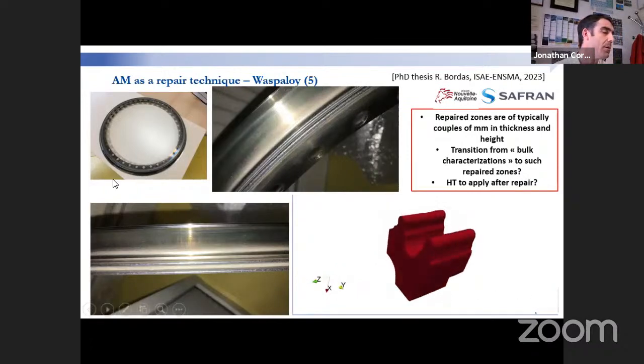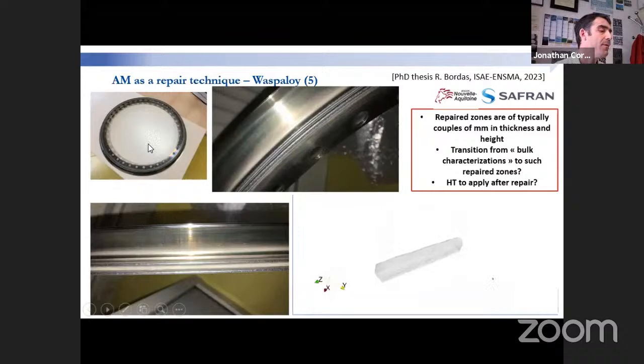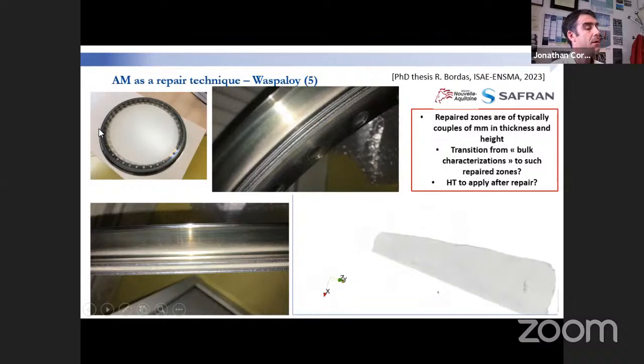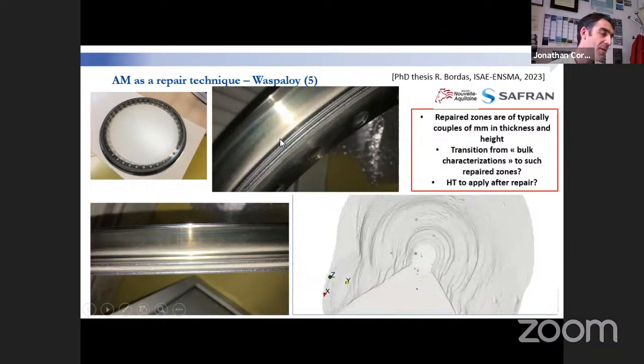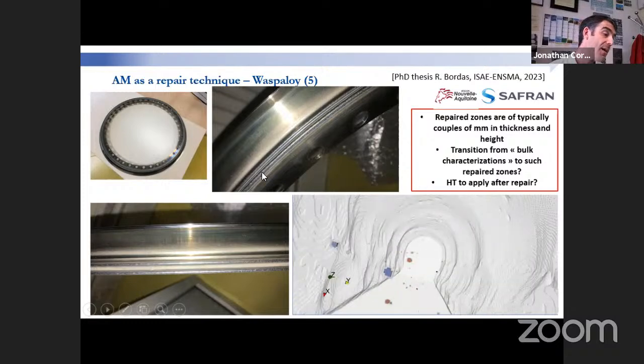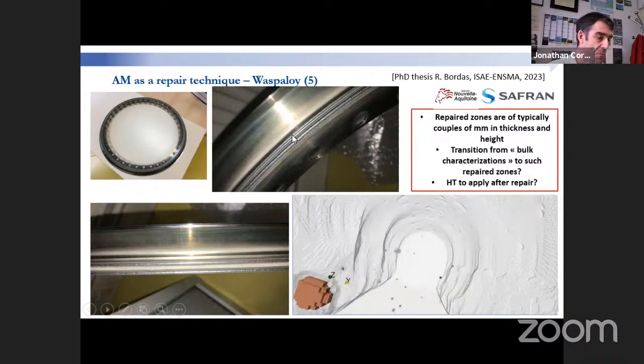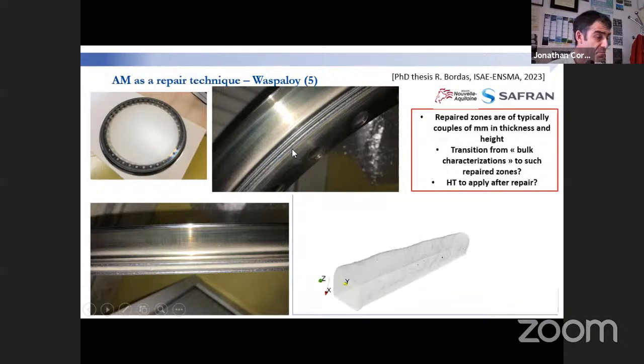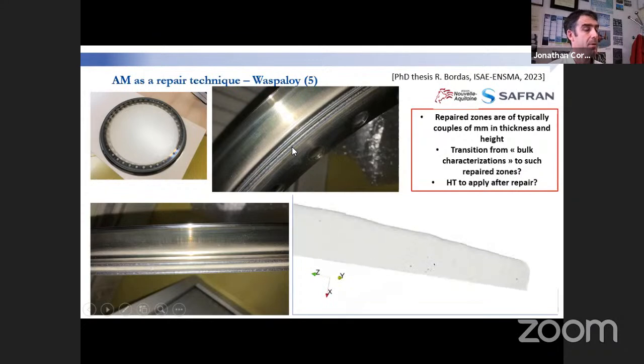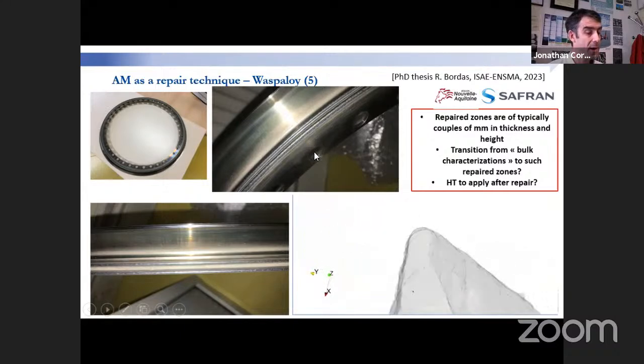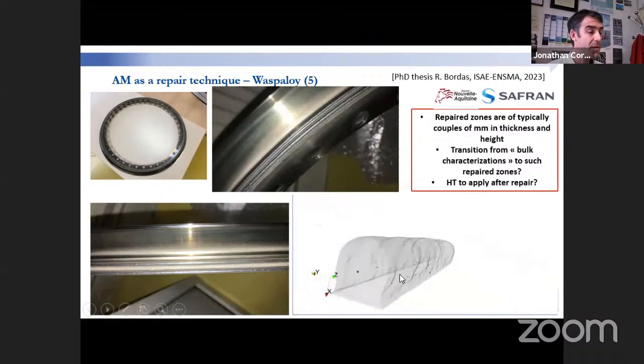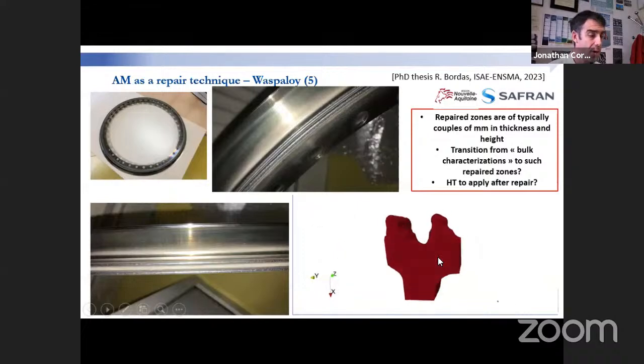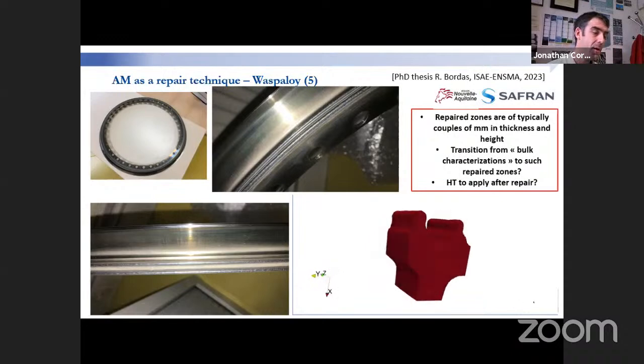So here is the typical component we want to repair. I cannot give the exact dimensions because that's confidential, but that's a part having a diameter of nearly 1 meter. And we are repairing the sealing parts here. The size of the sealing parts is typically a couple of millimeters in thickness. It means that here you have a tomography reconstruction of this kind of repaired part. And we have a given distribution of pores, which is typically different from the one we have in the walls.